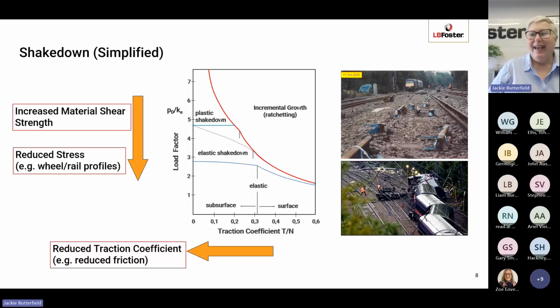So just to recap, anything to the left of that red line is acceptable and deemed to be safe. Anything to the right is to be avoided. So how we can change that behavior is that we can either change that K factor, the strength factor, so we can use a high grade steel, a high strength steel, or we can reduce the peak stress. And we can do that by changing the wheel and the rail profiles to change the behavior of the contact patch and the stresses in the contact patch. And the other thing we can do is to reduce that traction coefficient, i.e. to reduce the coefficient of friction. So obviously this is where friction management can take a leading role in preventing rolling contact fatigue damage.